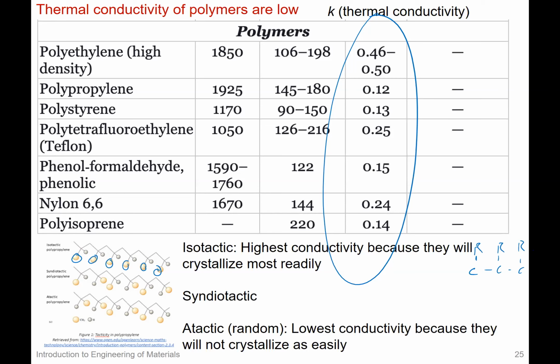They would have the highest conductivity because these types of polymers will crystallize most readily, even though 100% crystallinity is impossible to achieve, but we can get some pretty high numbers, and thus isotactic polymers will have the highest conductivity. Syndiotactic, all right, it's alternating, so you can see here on either side, and so the conductivity will be somewhere in the middle. And then of course, if you just have random functional groups where it could be on either side randomly without some reasonable periodicity, then these types of polymers will have the lowest thermal conductivity because they're not going to crystallize as readily, okay? And so when we look at the structure of polymers and also the mechanical properties of polymers, we can now also dictate and predict the thermal conductivity of polymers just based on where we know the functional groups to be and how they pack.